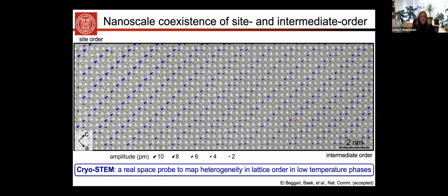Now, what's more interesting, and that brings us to heterogeneity, is we can now zoom out in a region of the film. And if you zoom out, what you will see is a transition from the top left to the bottom right, where you go from site-centered symmetry to intermediate order on the bottom right, with a transition region in between. And so what this shows you is that oftentimes in quantum systems, you have coexistence of ordered phases, and they coexist on the nanometer scale. And often bulk probes will not be able to get at those kinds of heterogeneities that exist in real space. So CryoSTEM really is a powerful probe to measure both local symmetries, but also variations and phase competition.